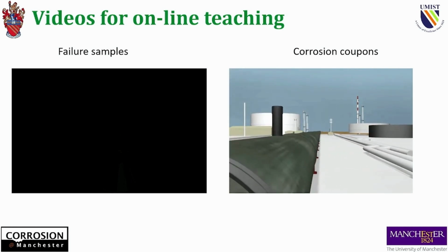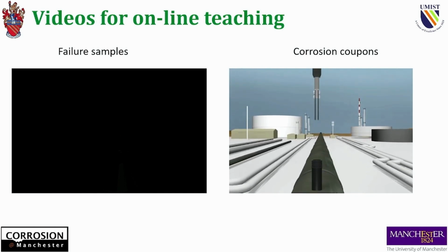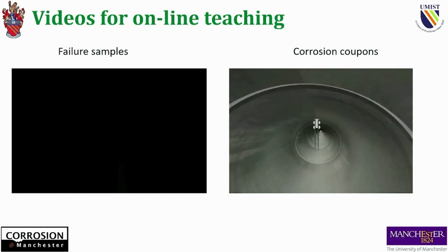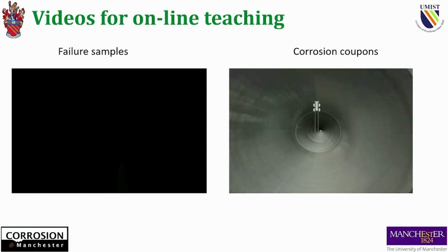So it's being weighed, and typically we will use 2 corrosion coupons inside the pipeline at any one point, so we get more reliable corrosion rates, and you'll see that here. You can see the corrosion coupons being mounted and entered into the top of the pipeline, and you can see them there dangling into the pipeline.